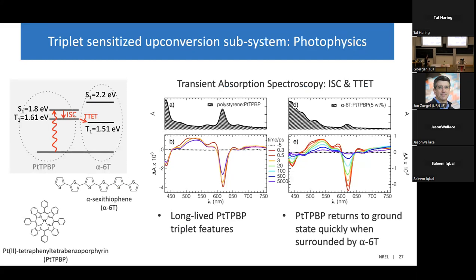However, when we embed PtTPBP within alpha-6T, the amplitude of the signal is significantly quenched, which suggests that the energy is being transferred from the triplet of PtTPBP elsewhere. And the answer is that it's moving over to the triplet state of alpha-6T.